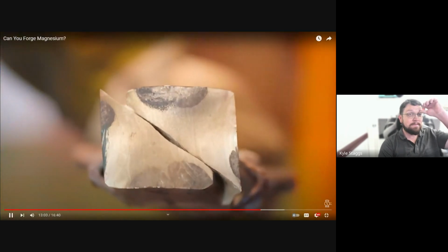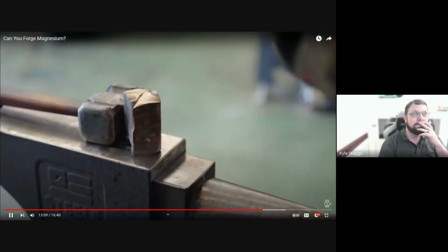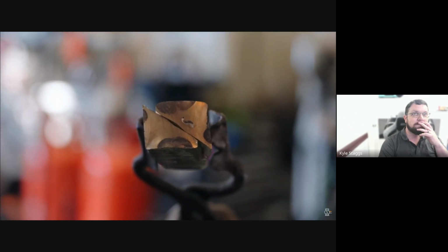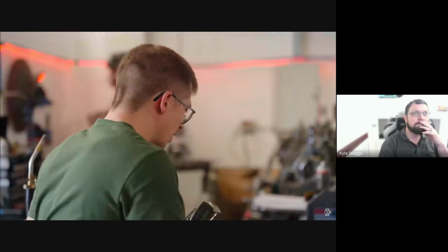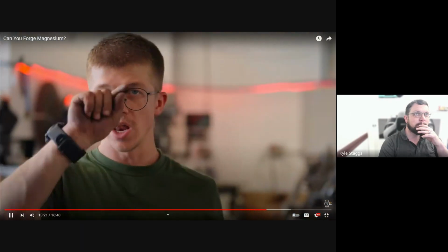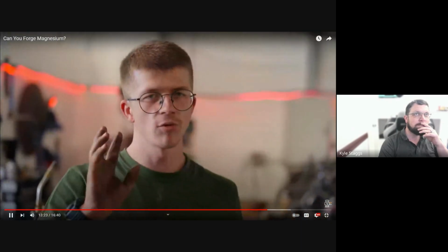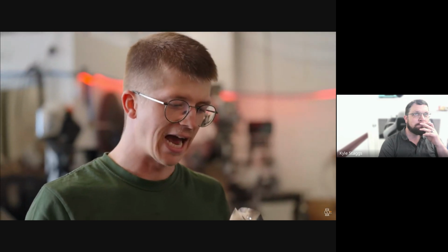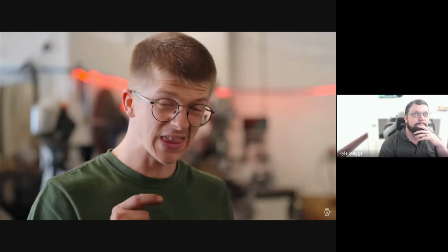Oh! We got just the slightest rhombus and it instantly ripped it apart. Wow! Straight down the diagonal. Get some! That is a work of art. Where's my touch mark? That is one bloody temperamental material. It's possible that it was getting too cold, but what I definitely know is that we went from a nice square cross-section to a rhombus, and it only took a few blows from there for it to rip. So it could be a combination of it cooling down too much and the rhombus, or it could be just the rhombus, but that's really temperamental.